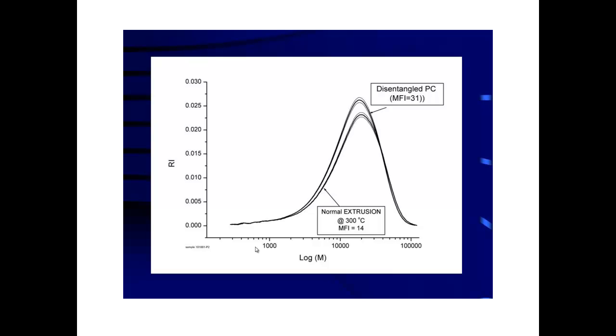The high molecular weight tail is also the same. There are some changes in the low molecular weight tail, but if we really compare and see whether it could have a plasticizing effect, it does not. It would basically correspond to, or explain, 5% of the results that we are showing, and not the 118% flow improvement that we see for PMMA, for instance.